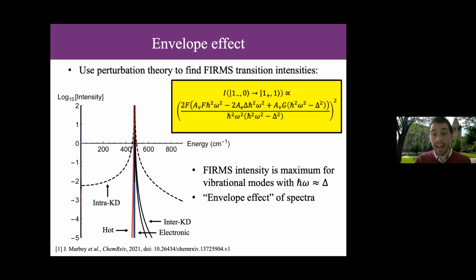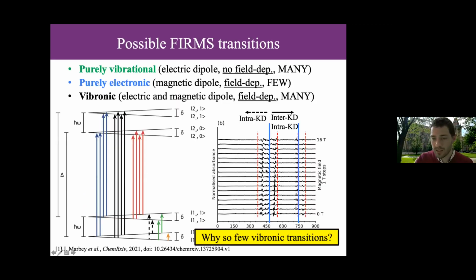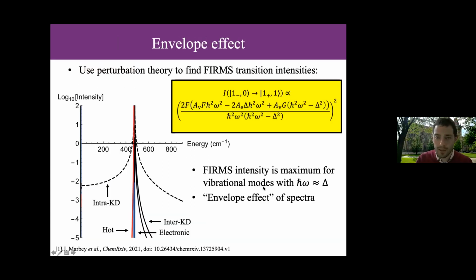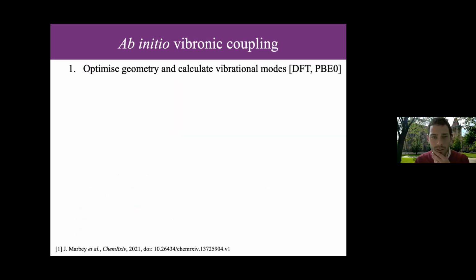Okay, and so when that extra vibration matches an electronic transition in your Hamiltonian, you get this increase in intensity. And so that's why we have this sort of envelope effect where you see these lots of transitions near your electronic doublets. But it doesn't mean that the coupling or the vibronic coupling of your other transitions are weaker than these ones. Okay, and that's a really sort of subtle point that's quite interesting, that's quite important.